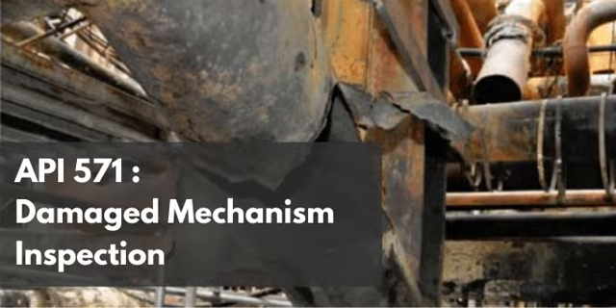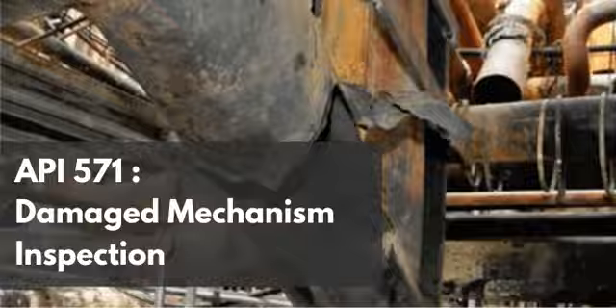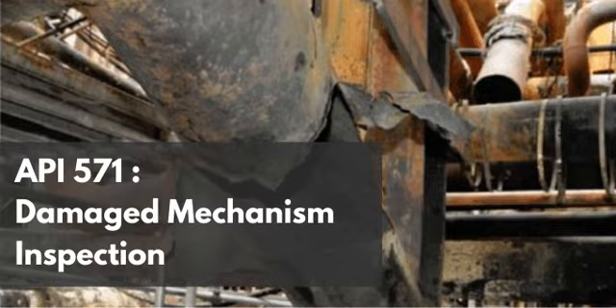Okay, let's unpack the physics of that triad, starting with the intergranular nature. We know that steel is a crystalline lattice, and those crystals form grains. Right. And the boundaries where those grains meet are inherently mismatched. Because the atomic spacing is irregular compared to the perfect lattice inside the grain itself, right? Exactly. The grain boundaries are regions of high energy and slight atomic disarray. Because of this structural mismatch, they become the paths of least resistance for chemical attack. As opposed to transgranular cracking.